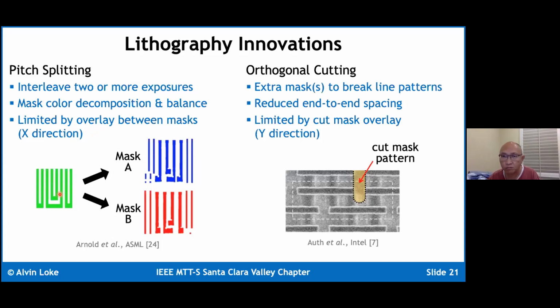Another thing you can do, which is done to reduce end spacing, is the use of an extra mask for orthogonal cuts. Okay, and so here the idea is that if you were to have features that ended because of near field diffraction effects, you would get a lot of rounding and corner pullback. But if you pattern a bunch of horizontal lines and with another cut mask you expose the breaks, you actually get much cleaner features here. And the idea here is that you may get near field diffraction rounding effects at the ends of your cut mask patterns, but because they're not part of the original features you're trying to slice through, you don't care.